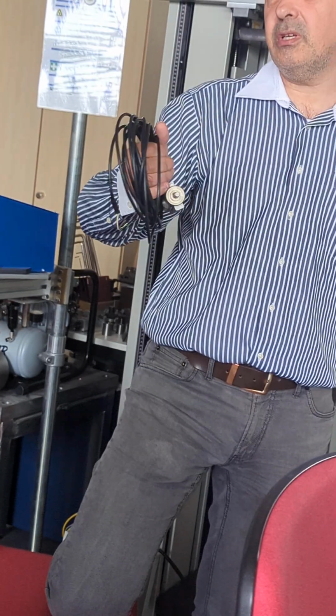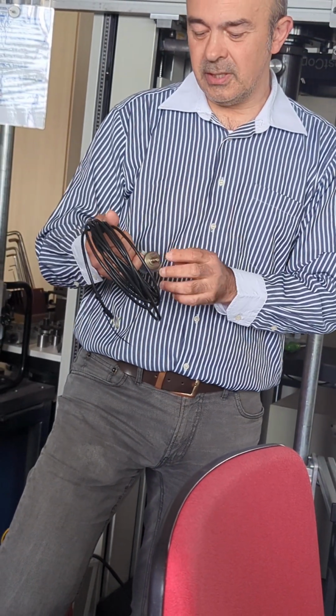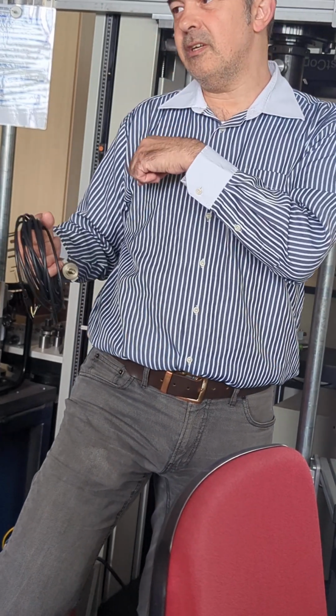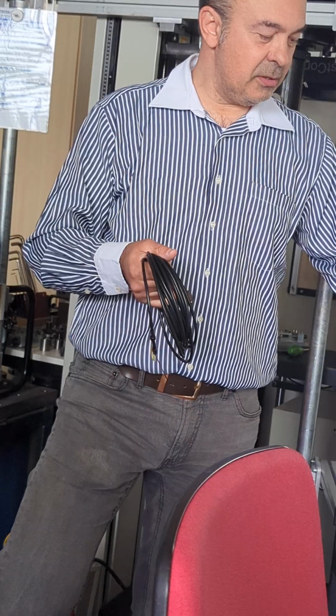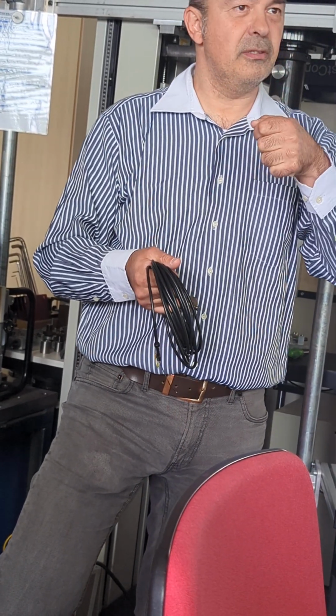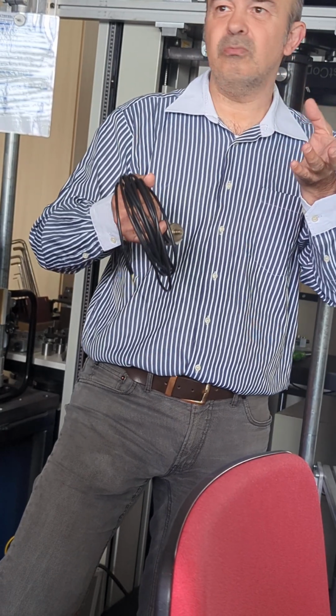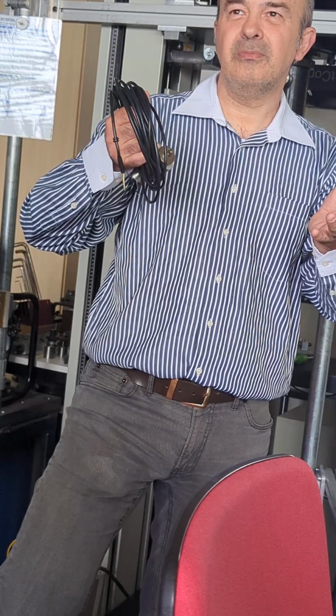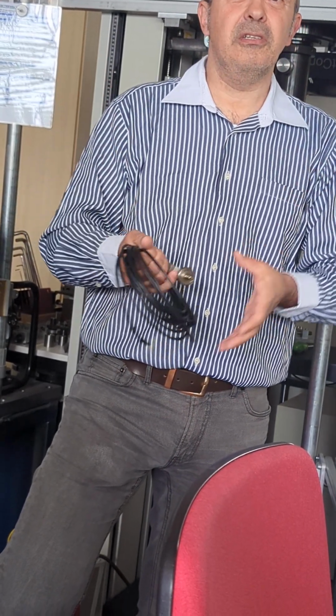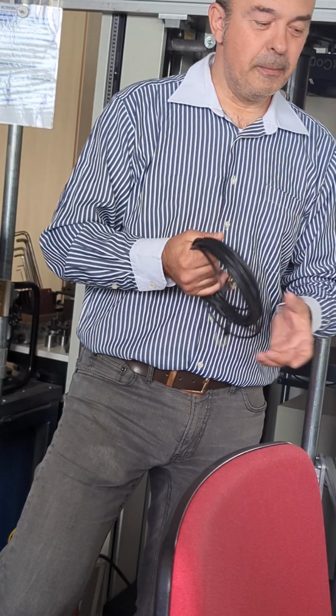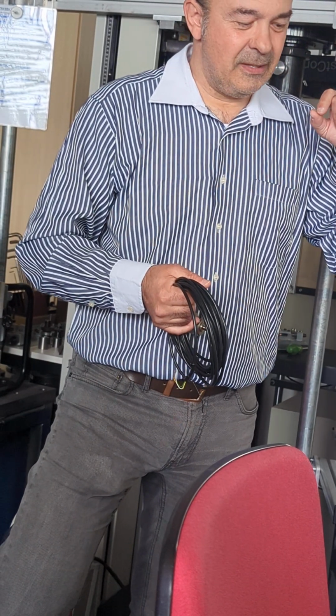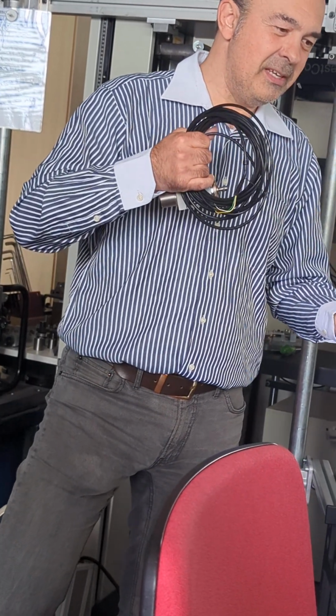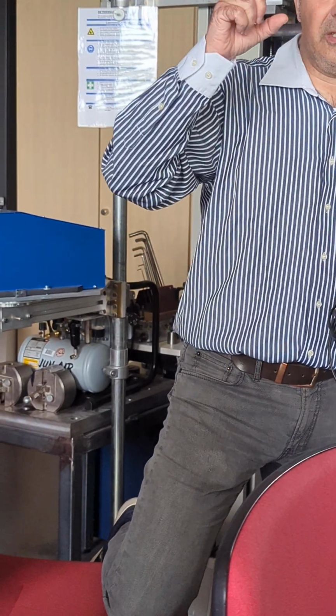On the side there are curves which show these experiments. We did it at 20 degrees, 50 degrees, 100 degrees, and we made creep tests, not tensile tests, but creep tests. It means we took the sample, hung it on a defined load, for example 10 Newton, 15 Newton, and then we wait to see what happens, to get the information we need. This elongation, we have to be very precise, and